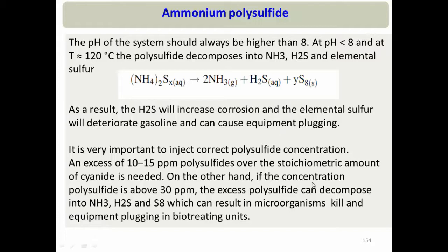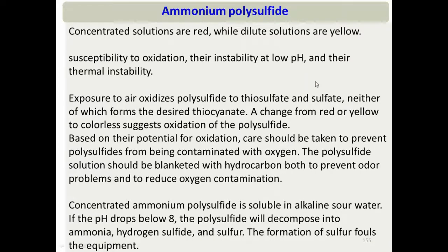But we should not increase the concentration above 30 ppm, otherwise the polysulfide will decompose and cause problems. Another important point about ammonium polysulfide is that concentrated solutions are usually red and dilute solutions are usually yellow. They are unstable at low pH, as we have already discussed. Another problem is that they are very susceptible to oxidation. If exposed to air, they oxidize and form thiosulfate and sulfate, neither of which forms the desired thiocyanate.